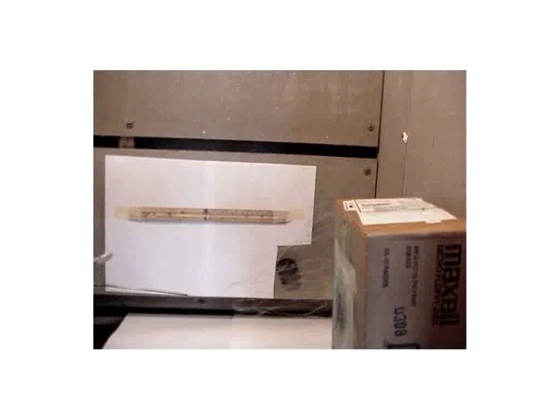The humidity is important, especially when you're going to do sensor work. Now, to electrospin, we basically do it in air, as you can see on this slide over here. But once we make a device, then you're right. It's important to control humidity because the current flowing through these fibers is very sensitive to the environment. In fact, if we have the fiber sitting on a table and somebody opens the lab door, then we can actually see the change in the current.